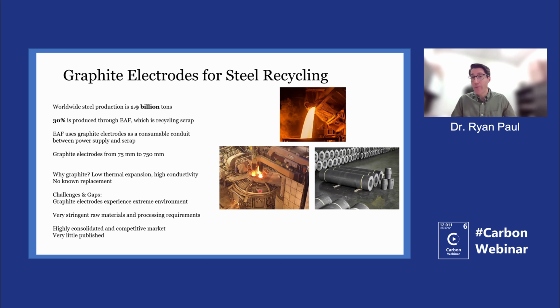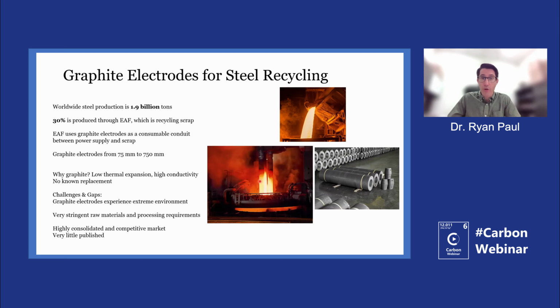And in order to accommodate different furnace sizes and different applications, graphite electrodes come from anywhere from a diameter of 75 millimeters to 750 millimeters. And these graphite electrodes, as I mentioned, are really the very critical conduit of passing the electricity down into the steel. So why is graphite used here, and why hasn't there been another material that's come in and replaced this? Well, graphite is uniquely positioned for its low thermal expansion, high electrical and thermal conductivity. And despite attempts to replace this or use other materials, there really is no known commercial replacement besides graphite electrodes, these cylinders that are used for EAF steel making. And as one electrode is consumed, another electrode can be placed on top of it, and you can continue making steel.